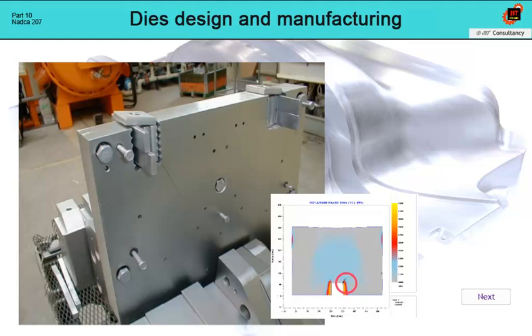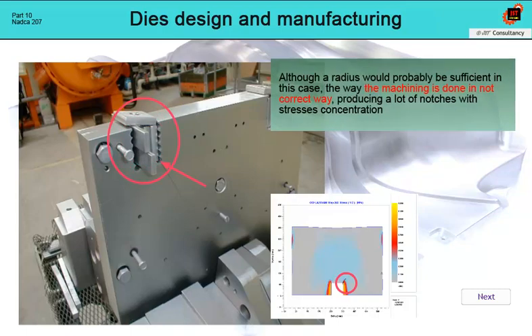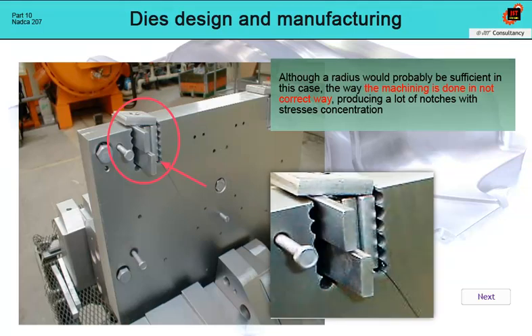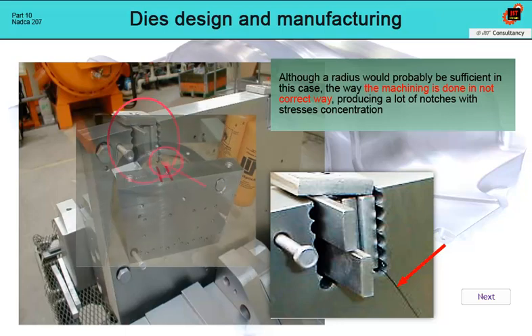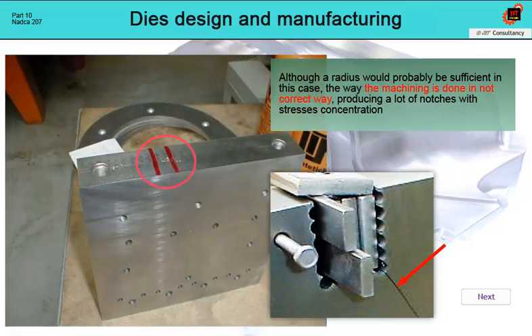In this case, although the designer could have thought of radii, the machining method created a number of notches, resulting from the inappropriately chosen distance of the drilled holes and the machining method. As a result of this choice, there are a number of places where a crack can be initialized. It is also necessary to remember this when preparing the insert for hardening. The most extreme case of such a crack in practice is a crack where the stress concentration was initiated by embossed letters on the plate periphery.